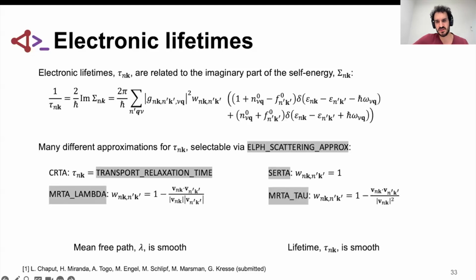There are two other approximations that are useful and used a lot in the literature, that is the momentum relaxation time approximation. There are two commonly used forms that differ in the approximations or how the derivation comes about. In one of them, MRTA lambda, it is assumed that the mean free path is smooth in K-space, while in MRTA tau, it is assumed that the lifetime is smooth. It is typically MRTA lambda that is more numerically stable.